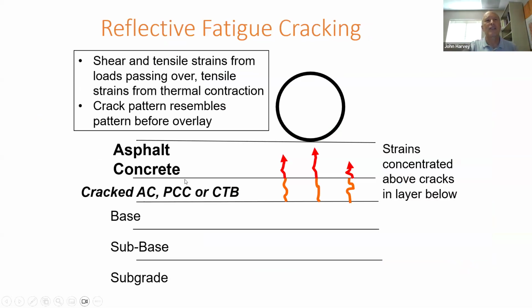If you have existing cracking in your asphalt or concrete or cement treated something under there, and you put new asphalt over the top, that is a stress concentration. And the same process of fatigue and age-related cracking, thermal expansion and contraction is going to open and close that underlying crack, and heavy loads are going to bend over that crack. Except now it's going to go faster, both of those processes, because it's a stress concentration, and that will drive that crack up to the surface. So if you're doing a mill and fill on existing cracked stuff, the cracking will tend to come up faster than if you had a solid new asphalt layer of the same thickness, even if it's 1.5 inches, because of